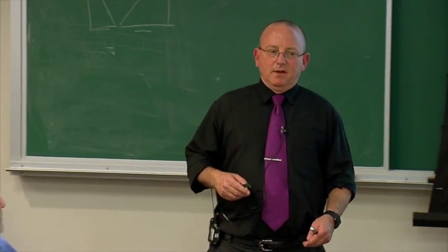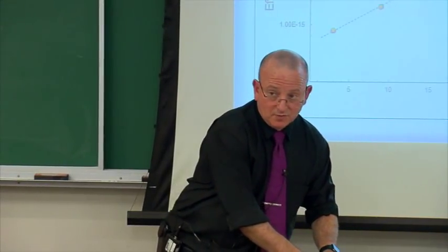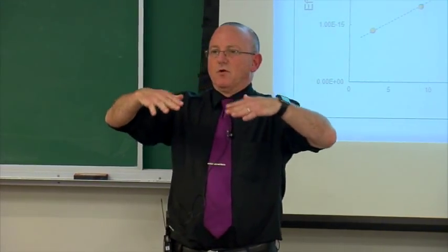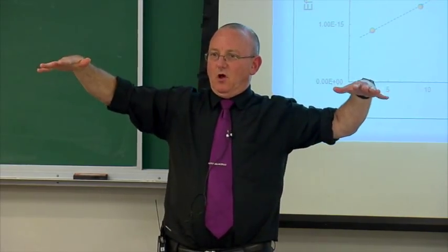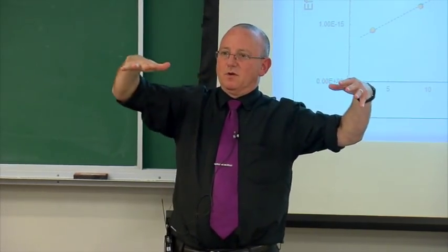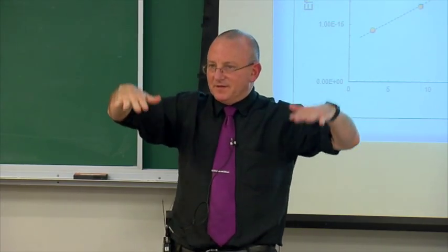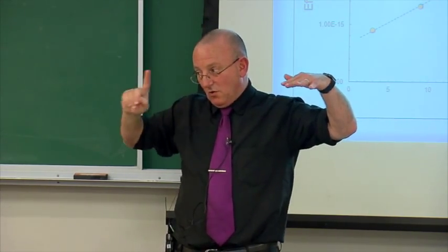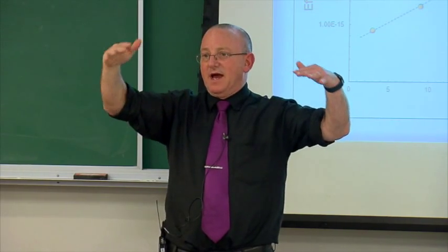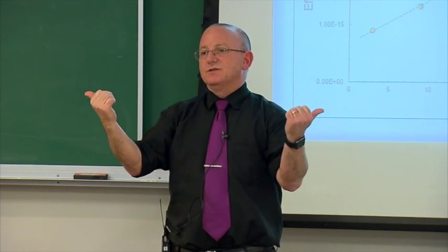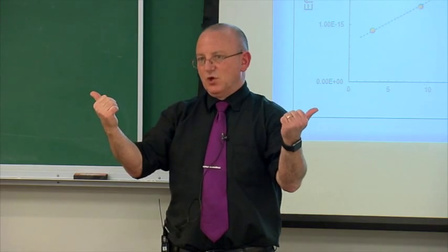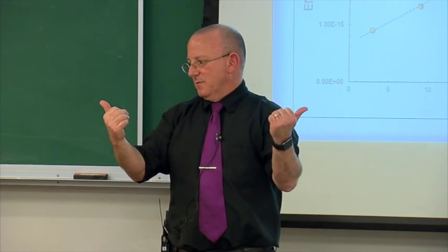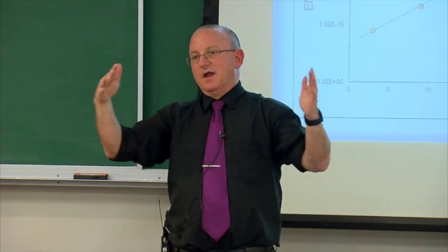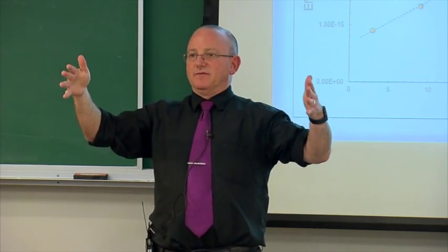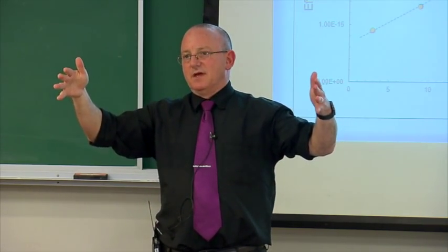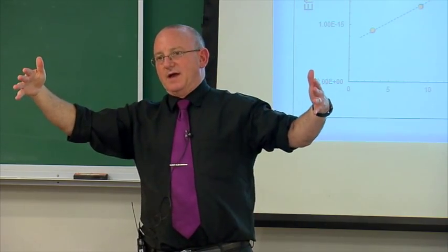What's happening here is that this is why we did the single crystal experiments. The basal plane is growing, you're getting plates, and these plates are elongated, and this is the basal plane, the flat part of these grains. So it's not that the basal plane is growing slower. It actually goes faster because of calcium, but this end is where all the action's really happening, and we were stupid and did diffusion bonding experiments of basal plane to the poly and not one of these prismatic planes, and that's what we have to do now. Something is happening at this end, and it's really going fast here.